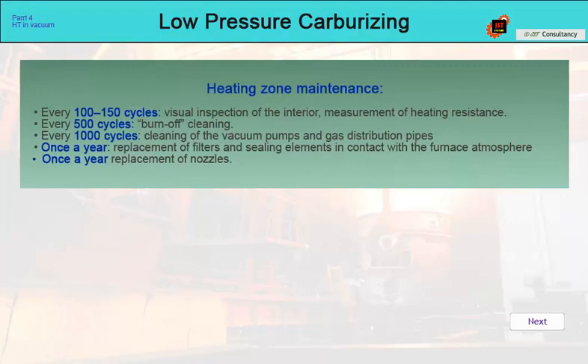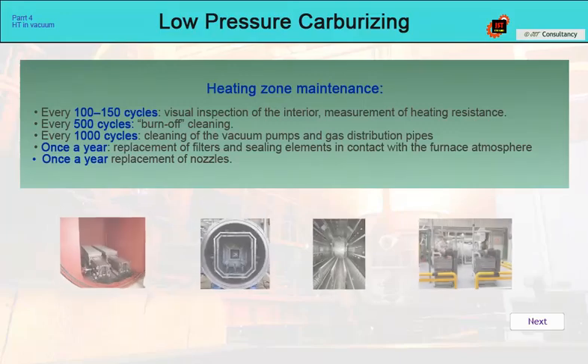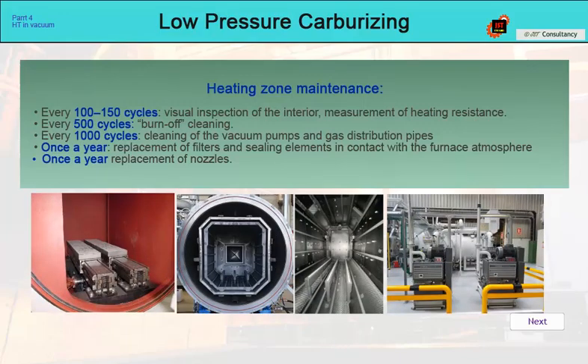From the point of view of heating chamber maintenance, it is recommended every 100 to 150 cycles, visual inspection of the interior, measurement of heating resistance. Every 500 cycles, burn-off cleaning. Every 1,000 cycles, cleaning of the vacuum pump and gas distribution pipes. Once a year, replacement of filters and sealing elements in contact with the furnace atmosphere and replacement of nozzles.